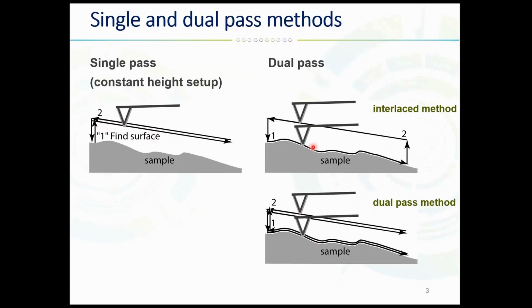Dual pass modes is an alternative to single pass. And what they do, they provide the topographical information of the surface along with the functional signal. So in interlaced mode, the forward pass records the topography of the sample. And then the tip is lifted above the sample during the backwards pass. In dual pass topography, it is like the same place is measured two times, forward and backward. And while we're going backwards, we are detecting the long-range signal.